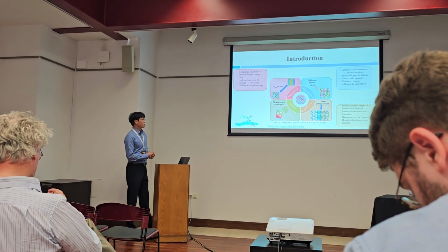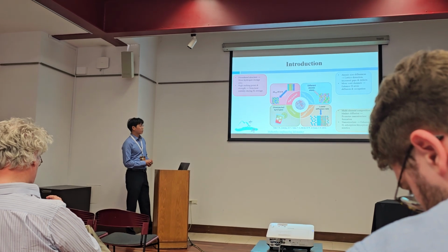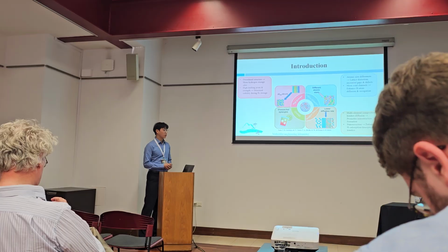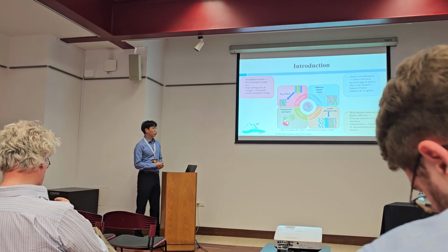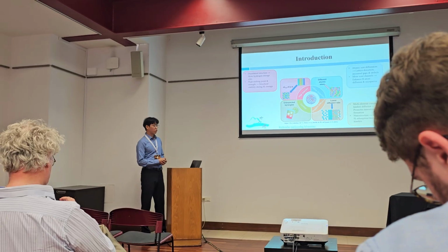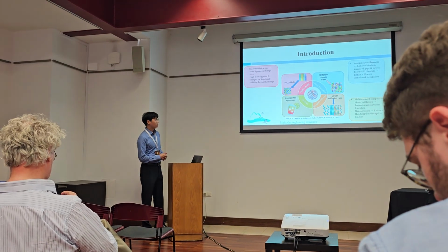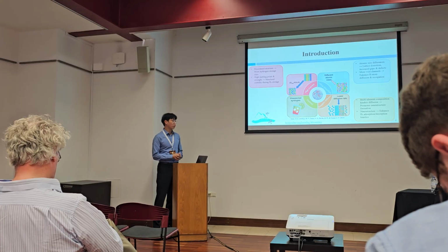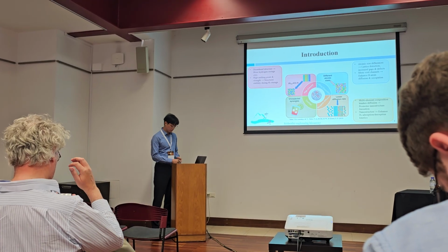Third is the sluggish diffusion effect, which results in a lower diffusion rate. Multiple element composition hinders diffusion and promotes nanostructure formation. Nanostructure enhances hydrogen absorption and desorption kinetics.